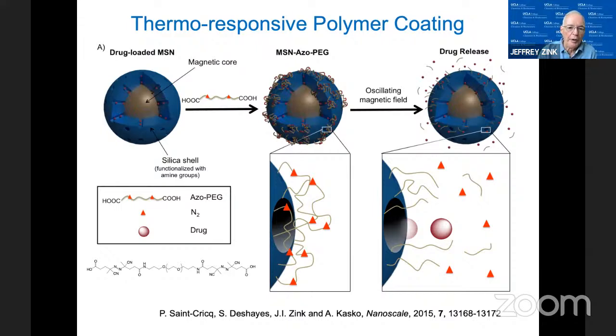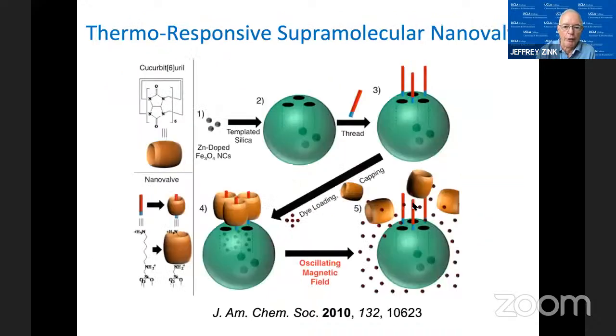And if we do that after we fill the pores with the drug, we're able to trap the drug. And then if we put it in the alternating or oscillating magnetic field, the internal heat breaks those bonds that causes the polymer to disintegrate. And of course, as the polymer comes off, it opens the pores and we're able to deliver the drug. So that was another early type of cap that we used.